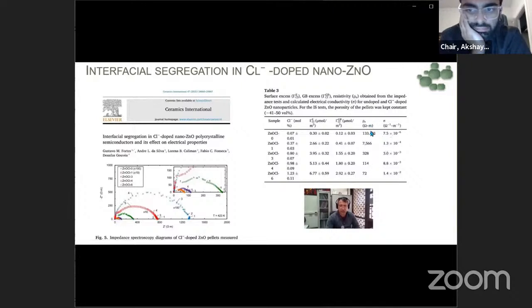Then you can see here the total resistivity decreases with chlorine, and consequently we have an increase of conductivity. And this semicircle here refers to the grain boundary resistance, and then you have a stronger decrease in the grain boundary resistivity, and this has as a consequence an increase of the total conductivity. This is very important to have more time of electrons and holes without any recombination, and then increase the